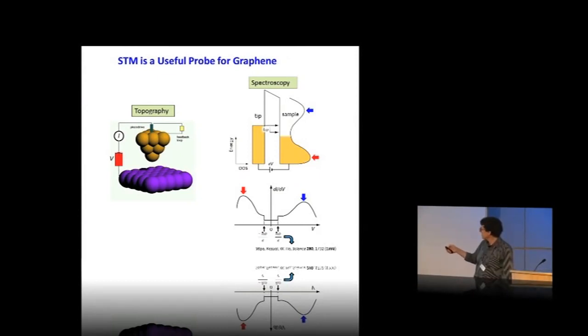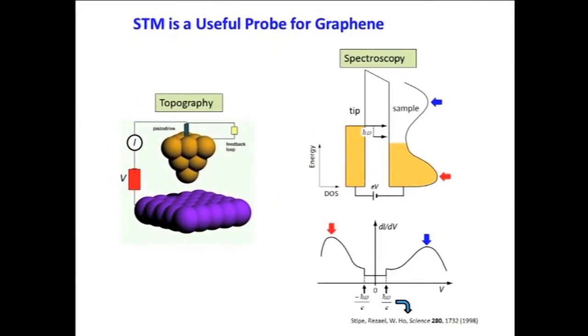And by measuring that as a function of the voltage between the tip and the sample, we can measure the energy dependence of the local density of states beneath the STM tip. And that's what this little cartoon is meant to show. And here, V equals zero is the Fermi level, and these are filled states, and these are empty states.